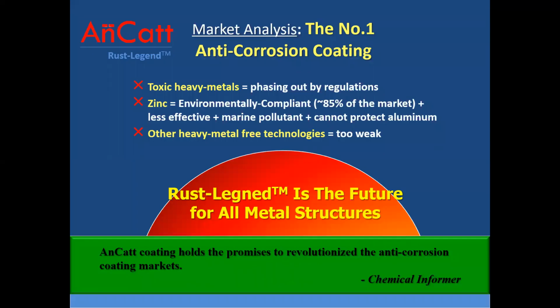The toxic heavy metals such as chromium and lead are being phased out by regulations. Zinc is the only environmentally compliant anti-corrosion pigment, accounting for 85% of the current market. However, it's less effective, requires frequent repainting, and it's still a marine pollutant that kills fish and marine animals, and is prohibited in seaports and certain open water. And it cannot protect aluminum, which is a major aviation material. Other heavy metal-free technologies are too weak in performance, unable even to reach the minimum high-performance requirement of 1,000 hours of independent corrosion tests. AnCatt Rust Legend is the future for all metal protection.